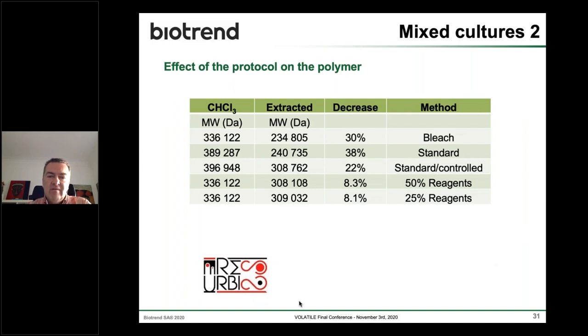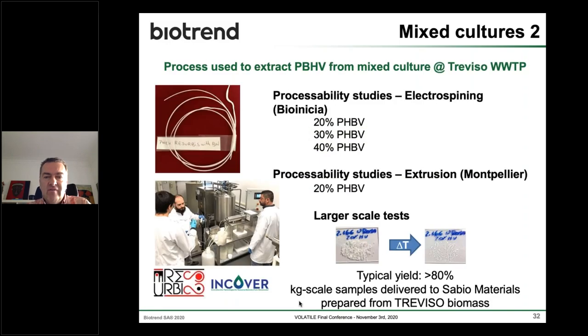And this depicts quite well the optimization that we did. So by decreasing the amount of chemicals and changing the composition of the chemicals, the decrease in molecular weight was very much reduced, and we preserved the native properties of the polymer, which was then validated. The usefulness of this polymer was then validated in different processability studies through electrospinning, for example, and extrusion.